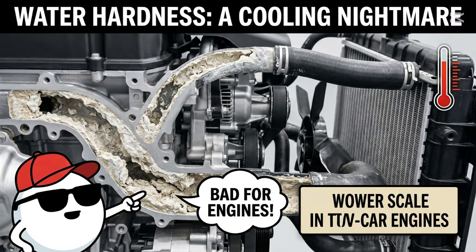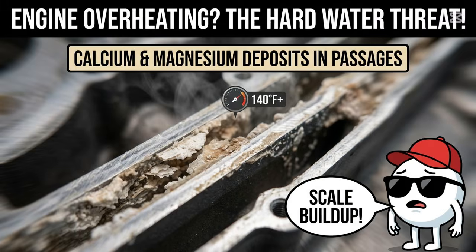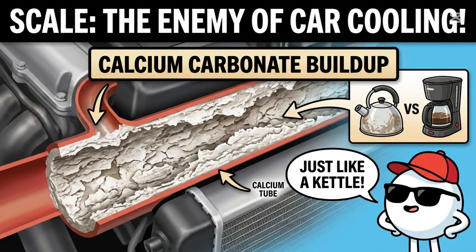The key property here is what water treatment engineers call hardness, essentially the concentration of dissolved calcium and magnesium ions in the water. Tap water in most American cities carries meaningful hardness, and that becomes a real problem the moment it gets hot. When hard water is heated above roughly 140 degrees F inside the narrow internal passages of your engine, those dissolved calcium and magnesium ions can't stay in solution anymore. They precipitate out and form hard calcium carbonate scale, chemically the exact same substance as the white crust you'd find built up inside an old tea kettle or coffee maker that's never been descaled.